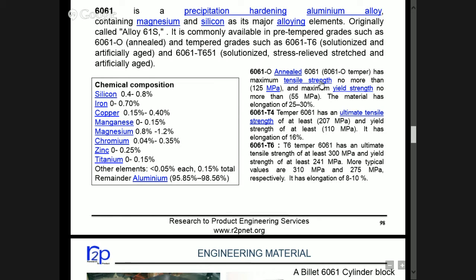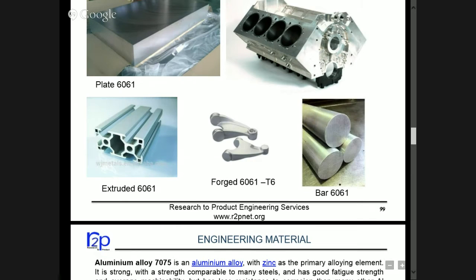So the tensile properties depend upon the type of heat treatment we do. While in annealed form the tensile is 125 megapascal, with the T6 tempering this goes up to 300 megapascal. So heat treatment is also very important in aluminium. It may be plates, or later on we will see in the casting also. Some of the components which are made in 6061: extruded tubes are there, then forged forks are there, even some blocks are machined out of it. So 6061 is very popular.